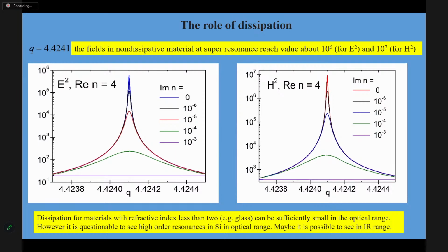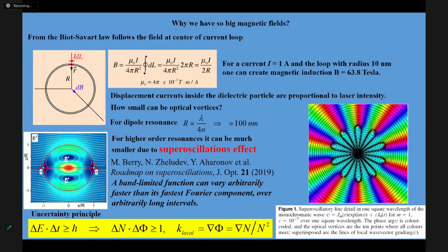The same effect you can see even with dielectrics. If you take, for example, silicon, the fifth resonance produces field enhancement, electrical intensity 1 million times and 10 millions for magnetic field. Then if you include dissipation, at a level of 10 to minus 3, this resonance disappears. So you need very transparent materials to obtain these resonances.